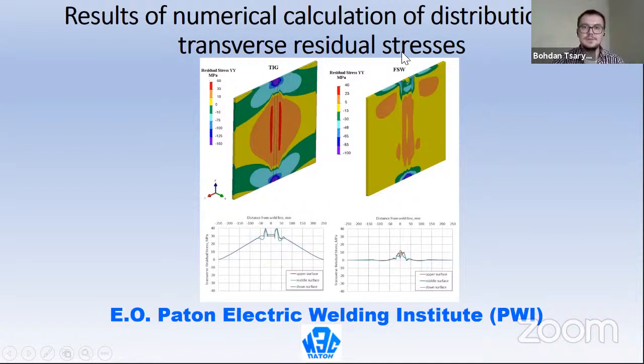But for transverse residual stresses, we have another situation. For transverse residual stresses for FSW, friction stir welding, they have a three times lower level than for TIG welding.